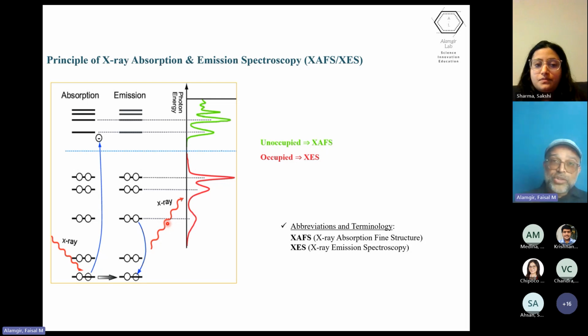Not only that, but also about the details of the chemical bonding and the type of ligand that the atom may have around it. But to put it in terms of electronic structure, simply, X-ray emission is essentially giving you the occupied states, densities of occupied states. The X-ray absorption is giving you the densities of the unoccupied states. So they are complementary to each other in that sense.